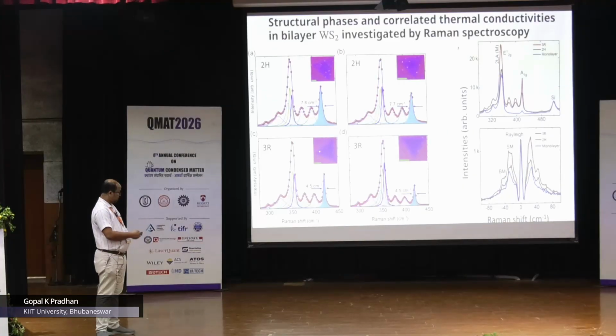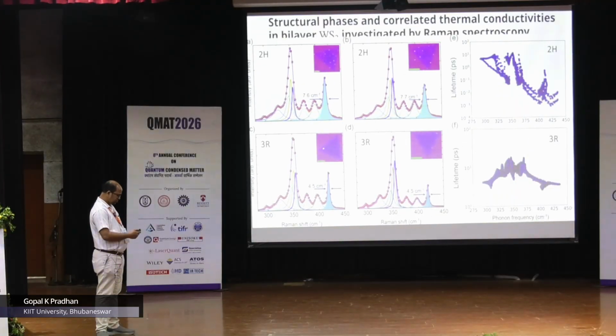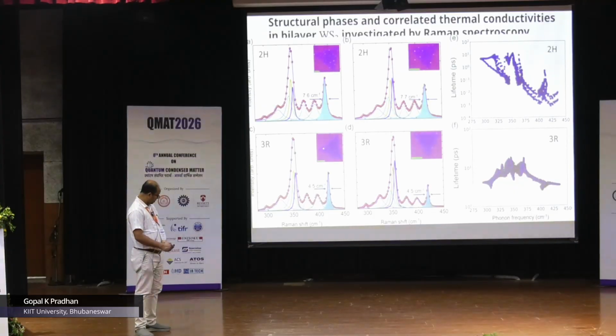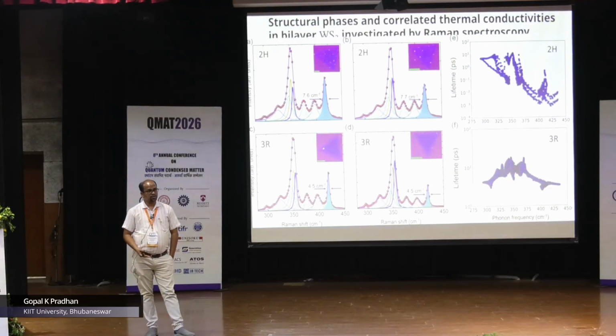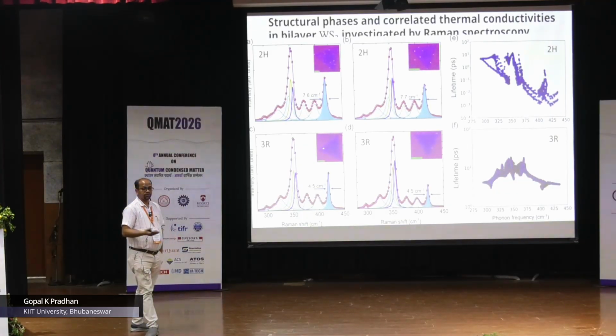So this is something that you can do, and then our collaborator from IIT Madras, Professor Nanda, did this calculation of the different phonons of the A1G modes, and you can see here, if you look at the 3R versus 2H, their lifetimes are very different. Okay, you can ask me why the lifetime is different. It is quite clear, because the full widths at half maximum are different. So that would translate to different lifetimes, and one is smaller than the other.